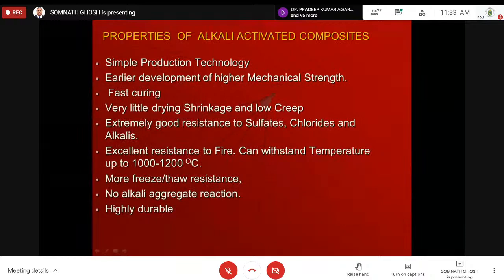You can develop higher mechanical strength, very high composite strength, you can achieve within a short time. Fast curing can be done. Shrinkage and creep can be avoided to a great extent. Extremely good resistance to sulfate, chloride and alkalis. Excellent resistance to fire, at least up to 1200 degrees, I have personally worked on it, and very good. Freeze thaw we have tested, very good. And you will slowly understand that there is no question of excess alkali within the composite, because when the reaction takes place, the alkali is consumed. So there is no excess alkali present, and that means no alkali aggregate reaction, highly durable, right?